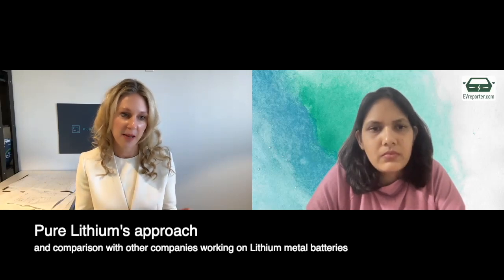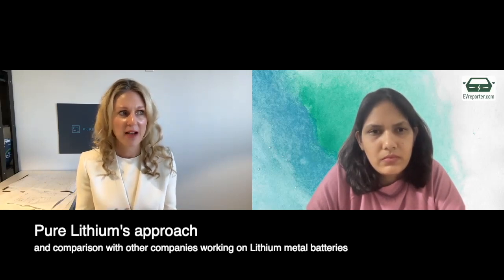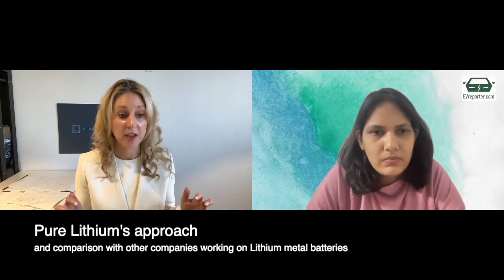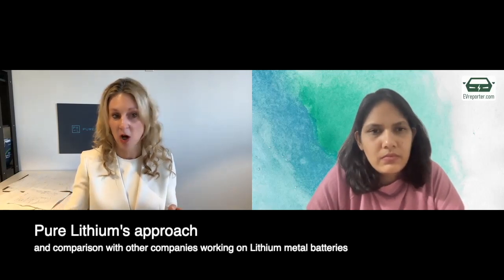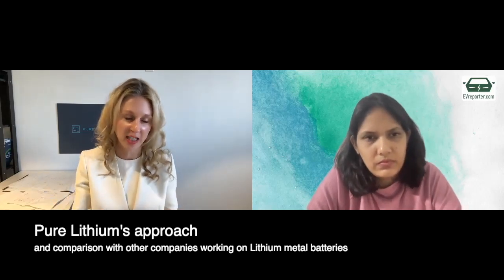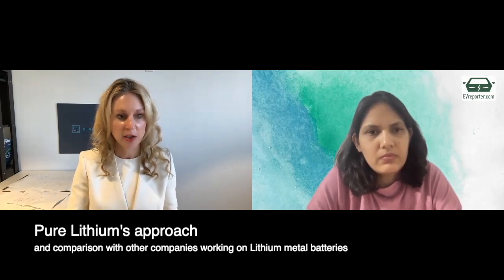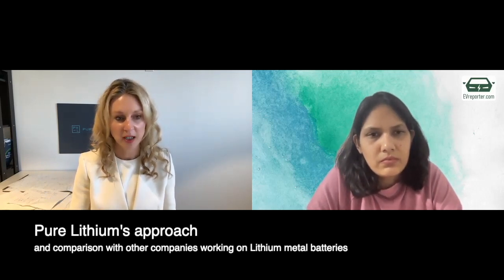When you make a lithium ion battery, you have between 1.5 and 3 weeks of what are called formation cycles. And that's sending the lithium that's all in the cathode over to the anode. And that has to be done in situ. So with lithium metal, you can turn product a lot faster.